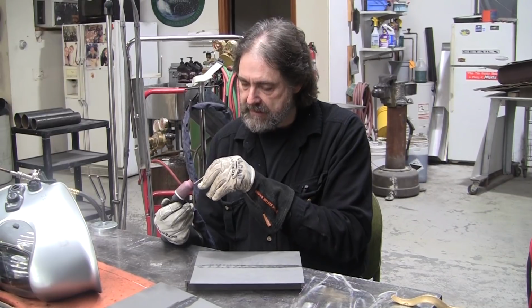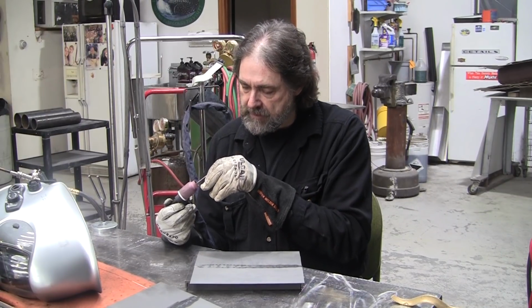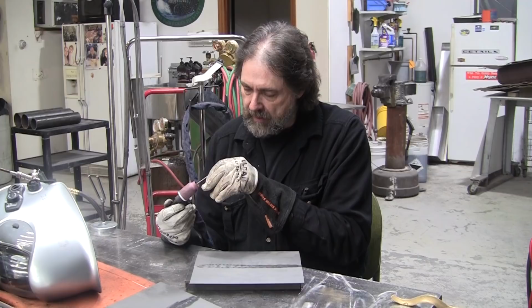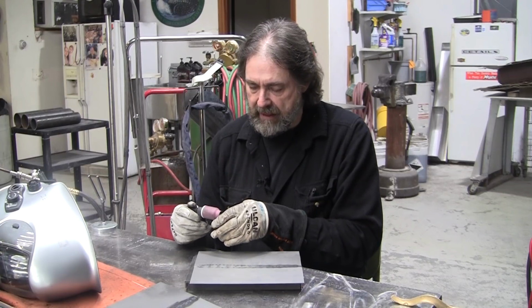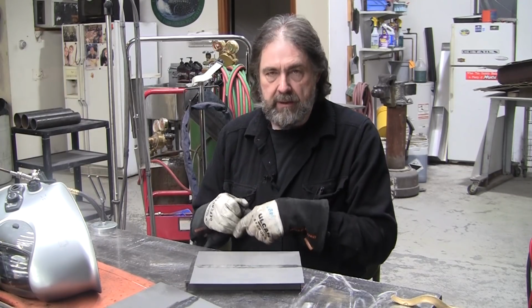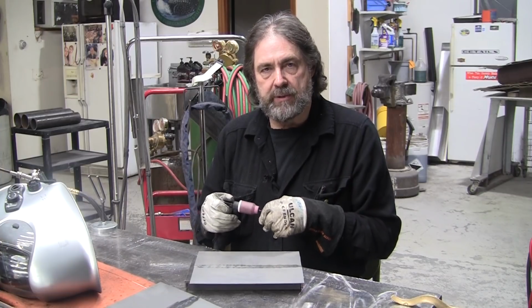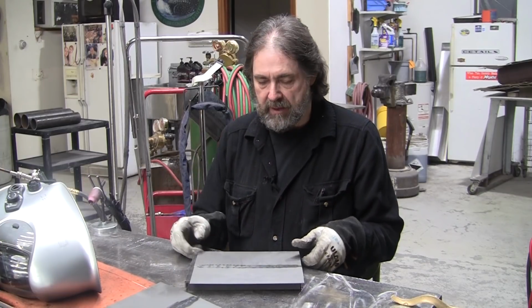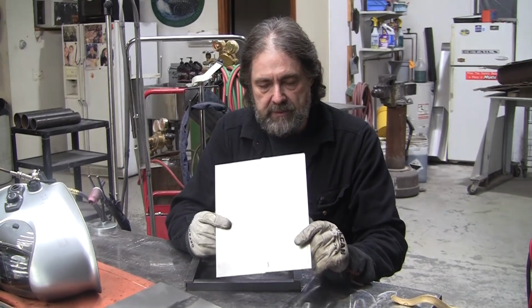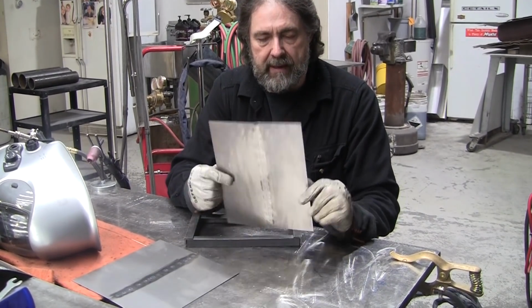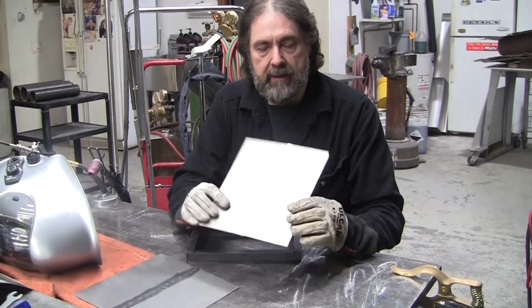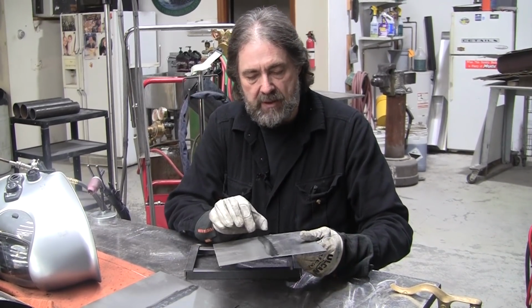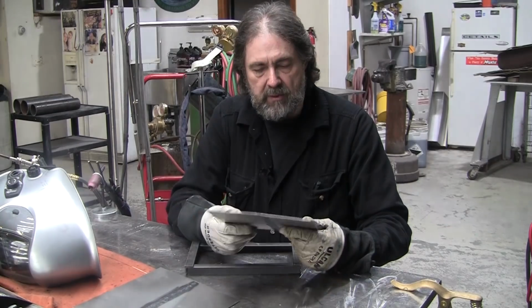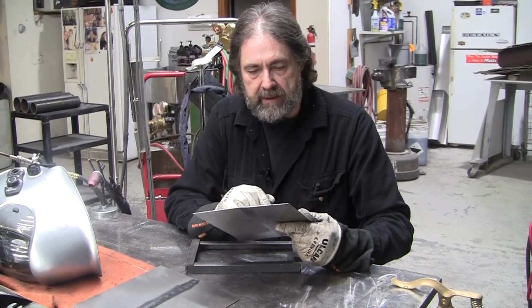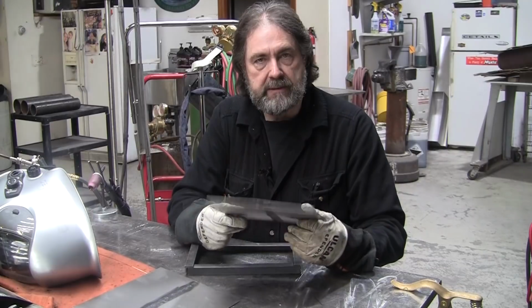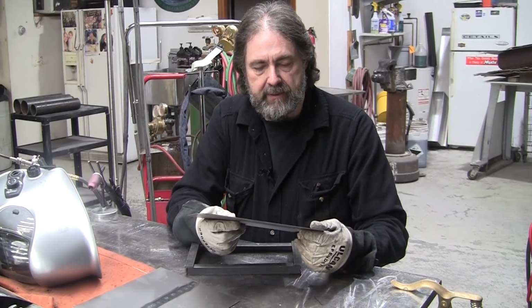And I tacked this together already, fusion tacks with the TIG. I just can't imagine that you can tack with gas as well as you can fusion tack with a TIG. The fusion tacks with a TIG are just incredibly simple to do, and the heat affected zone is tiny. There's no distortion of the panel, and they weld all the way through. The penetration's all there. You couldn't ask for a better tack.